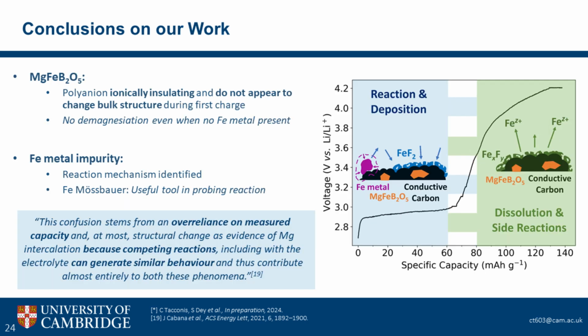So as a conclusion from the PhD project that I've been doing so far, when looking at our magnesium-ion pyroborate in the system that we're looking at with the lithium, we conclude that it's ionically insulating and doesn't appear to change bulk structure. We did a few attempts in magnesium electrolytes, but they didn't really go very well at all.